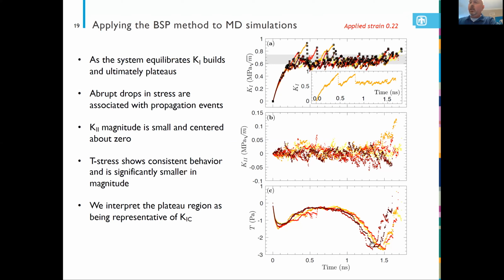I note that the T stress, although very interesting, is actually 6 orders of magnitude different than the K1 and K2 stresses, and so I disregard it simply because it seems to be irrespective of the stress state. Note that our fracture sample was loaded in K1 stress, so we would anticipate that K2 should be darn close to 0, and that is indeed the case. We find that the K2 stress is very much localized about 0, and that's excellent.